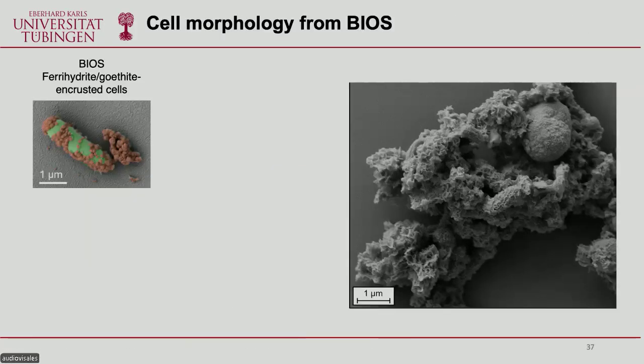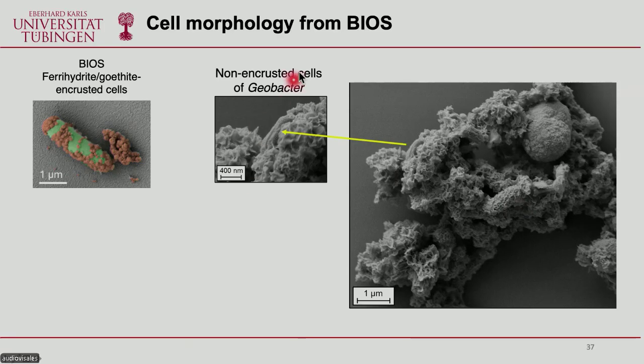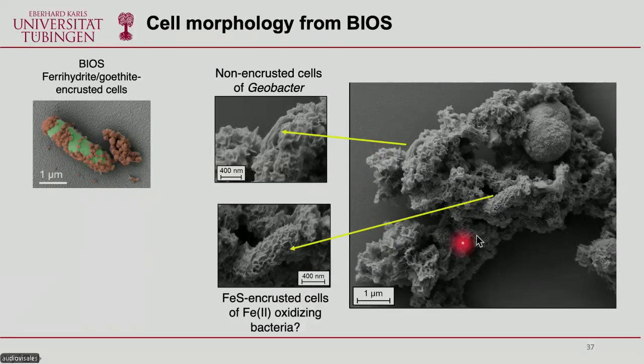And I just want to highlight also a couple of observations from these experiments. Using BIOS as the initial material, we saw that there are some cells with this wish-like structure. We think that these are geobacter and they are not encrusted. And at the same time, we see this cell right here, which has this encrustation by something, most likely goethite. And this seems to be like an iron sulfide encrusted cells of iron oxidizing bacteria.